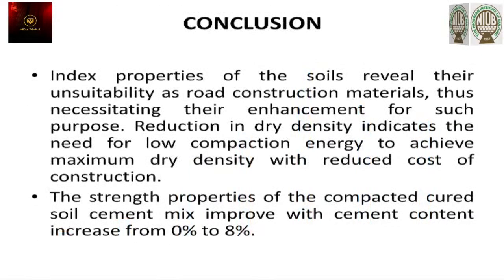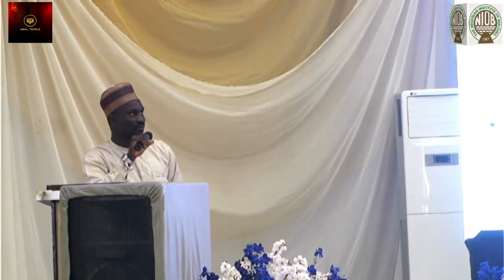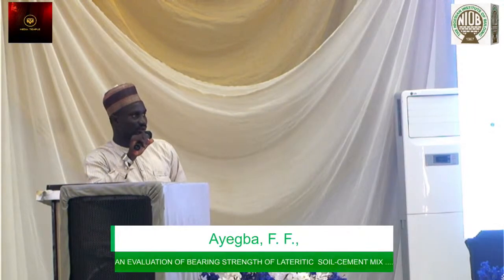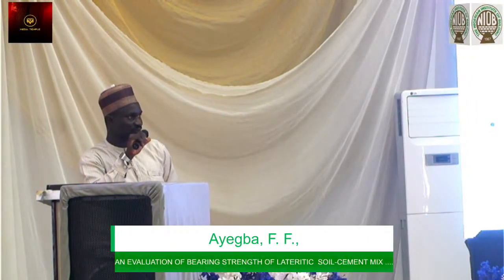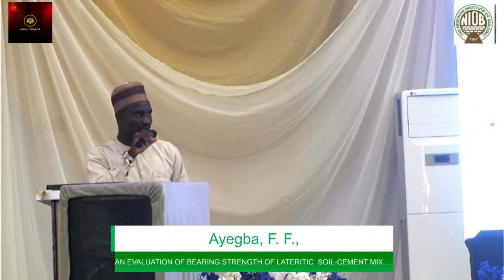And the conclusion. From the study carried out, we came up with this conclusion: that the index property of soil reveals their unsuitability as road construction material based on the A6 classification of AASHTO, thus necessitating their enhancement for such purpose. Reduction in dry density indicates the need for low compaction energy to achieve maximum dry density with reduced cost of construction. Then the strength property of the compacted cured soil mix improves with cement content from 0 to 8%.